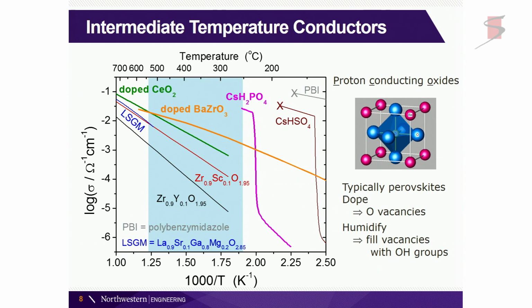that we use in my laboratory, but I'm going to talk to you primarily about this oxide here, which is an oxide which we can make into a proton conductor by modifying the chemistry such that it has some oxygen vacancies in it, and then expose it to high humidity, in which case the vacancies are filled up by hydroxyl groups. A second proton attaches to a second oxygen atom in the structure, and then these protons at these hydroxyl groups can jump from one site to the next, and that gives us good proton conductivity. So it compares here with some of the polymers, the highest temperature capability polymers out here.